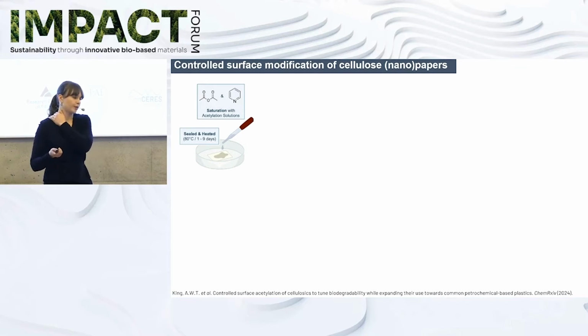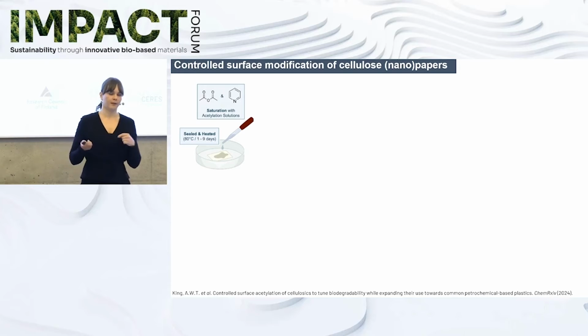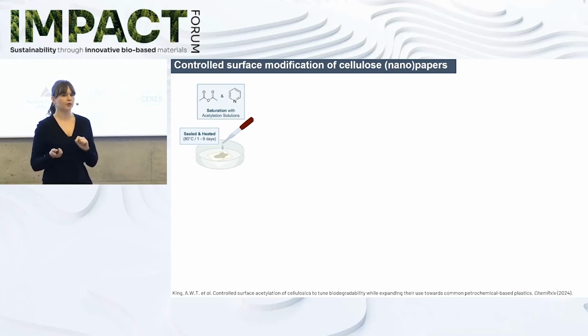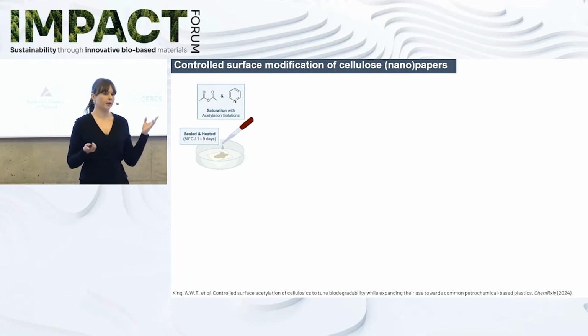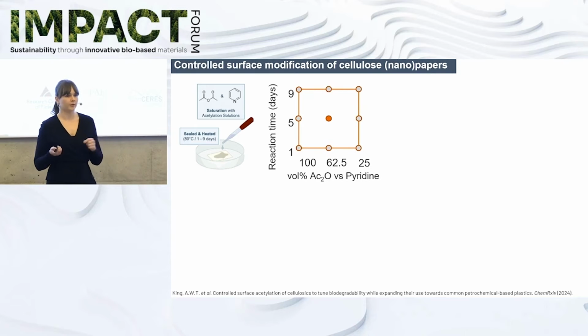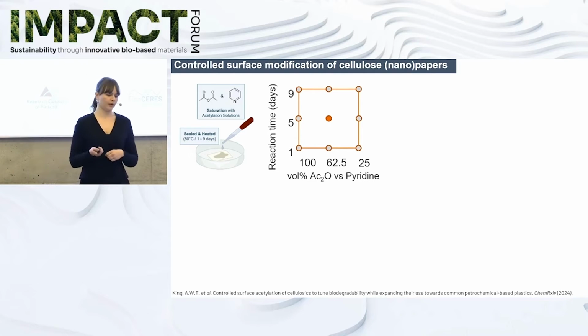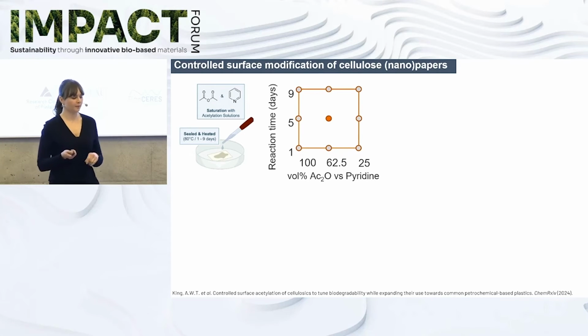So then to the controlled surface modification. This is from a recent paper from Alistair King and others, where they did this controlled surface modification on cellulose nanopapers and papers. Basically you have a paper or nanopaper substrate, and then you put it into these acetylation reagents, and then you keep it at constant temperature. The variables that were changed here were the reaction time and the volume percent of acetic anhydride, and the rest was pyridine. So these represent 9 different test points, and here we utilize this design of experiments to see how the variables will affect the modification and also the biodegradation.